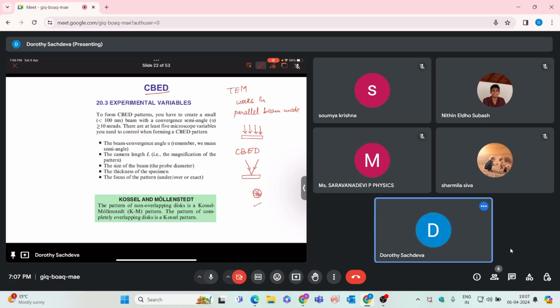So here the convergence angle will be this one. To form a CBED pattern, you have to create a small beam with a convergence semi-angle alpha greater than 10 milliradians. There are at least 5 microscope variables you need to control to form the CBED pattern. First, the beam convergence angle, this angle alpha, then the camera length L. In diffraction, we can change it using the magnification. Also the size of the beam, the probe diameter, should be small. The thickness of the specimen should be higher. And the focus of the pattern, whether it is under focus or over focus. So these are also known as Kossel-Möllenstedt, or basically your KM patterns.